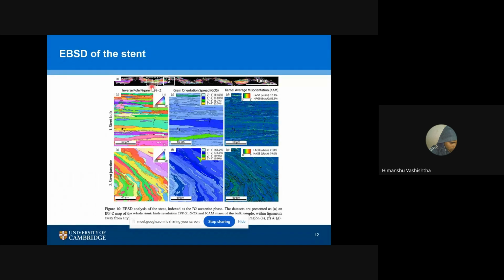So what we are capturing, the EBSD patterns up to point one - there is no edge or curve in the stent, so the first point is showing us up to that point. Second is where the stent is bending, we have captured the stent junction. That's called inverse pole figure, IPF. Second thing is grain orientation spread, and the third thing is kernel average misorientation, KAM maps.